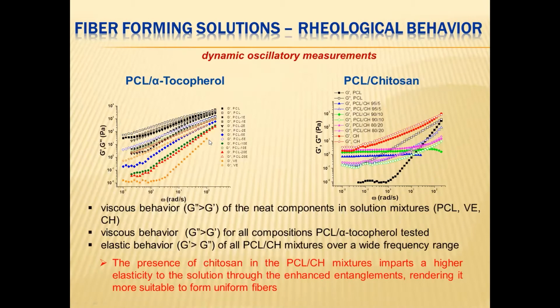The dynamic oscillatory measurements evidenced a viscous behavior for the main components of the mixtures prepared, namely PCL, vitamin E, and chitosan. Also, viscous behavior for the mixtures obtained from PCL and alpha tocopherol, while the mixtures of PCL with chitosan presented elastic behavior over a wide frequency range, with G' values almost independent of frequency. Therefore, the presence of chitosan in the mixtures imparts a higher elasticity to the solution through the enhanced entanglements, rendering it more suitable to form uniform fibers.